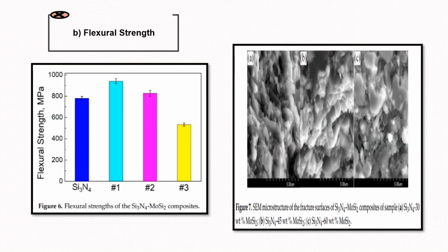Figure 6 shows the flexural strengths of the silicon nitride molybdenum disilicide composites. The flexural strength of the composite reached 942 megapascals, which was higher than that of the pure silicon nitride, which was 781 megapascals, when the filling content of molybdenum disilicide reached 30 weight percentage. However, the flexural strength started to decrease with increasing molybdenum disilicide content over 30 weight percentage. The flexural strength decreases to 535 megapascals when the molybdenum disilicide reached 60 weight percentage.